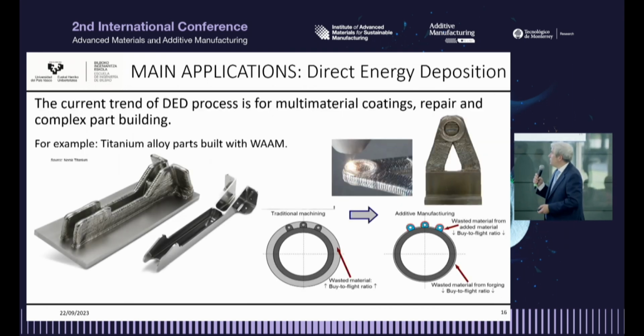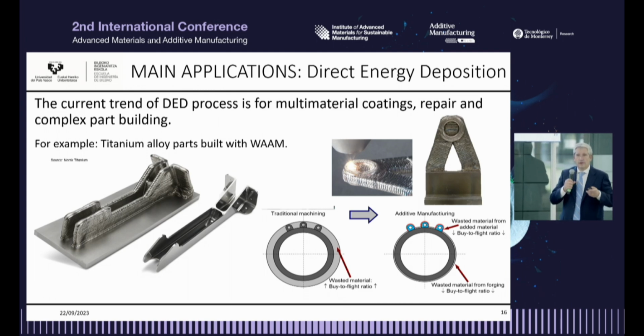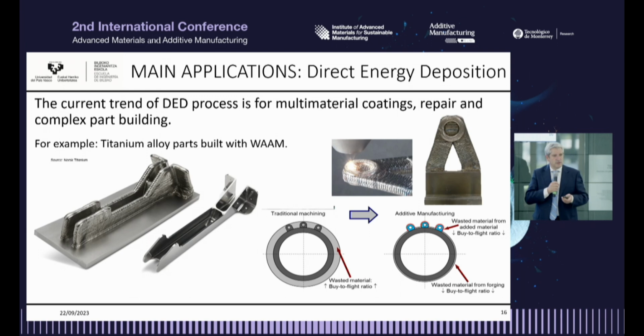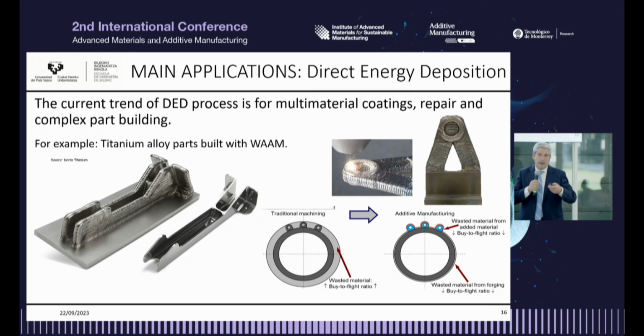This is an example from Norsk Titanium, a Norwegian company. This is a titanium part made by wire arc additive manufacturing, and it's a structural part already flying, already certified. And in this other example from our lab, it's a hybridization between forging, where the substrate is forged, and then we deposit this structure in order to reduce the volume of material, increase the efficiency in terms of material, and reduce the buy-to-fly ratio. So we buy less material in order to increase the efficiency.